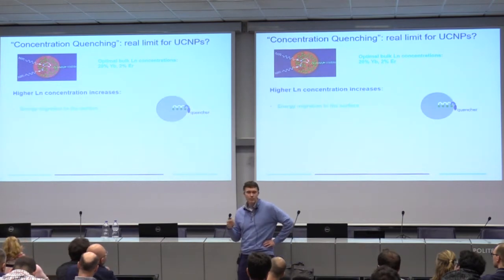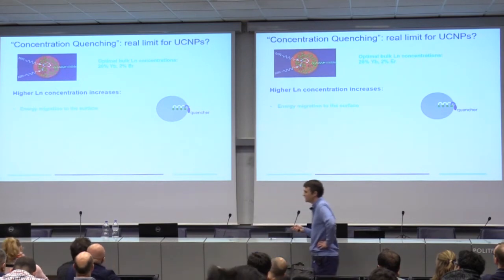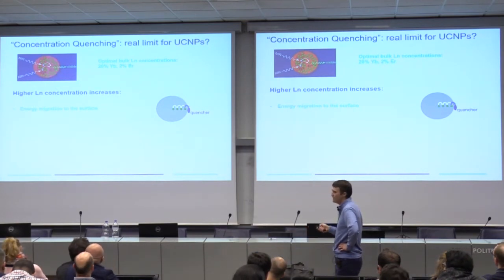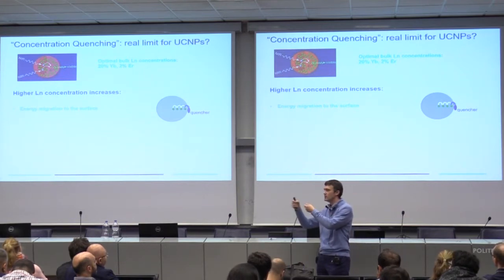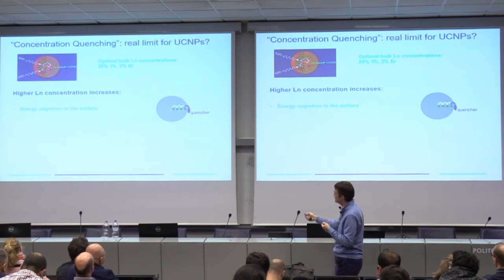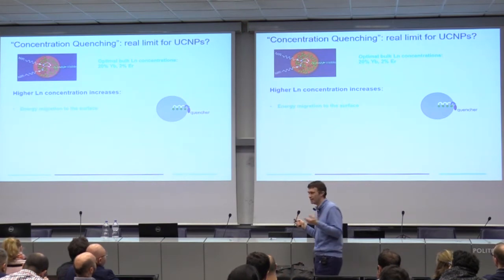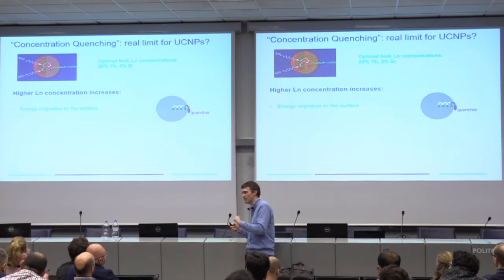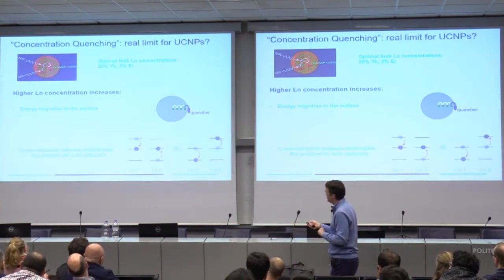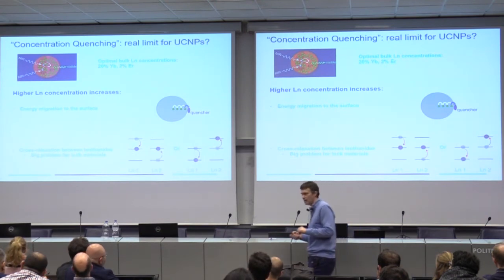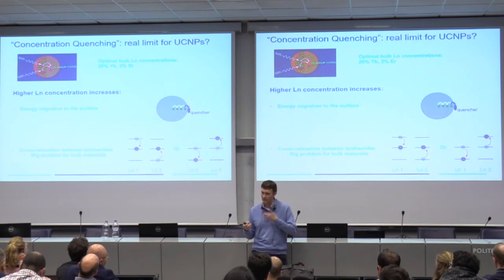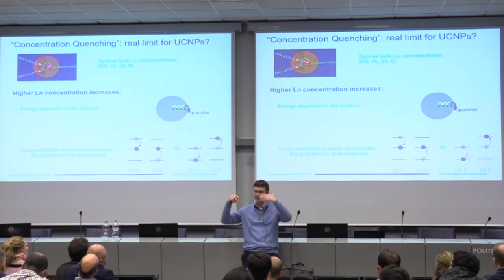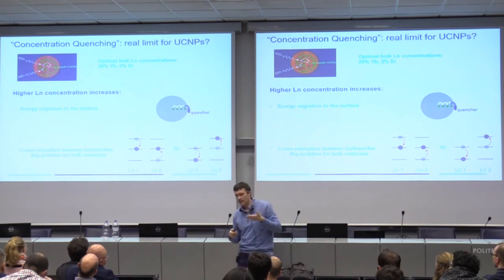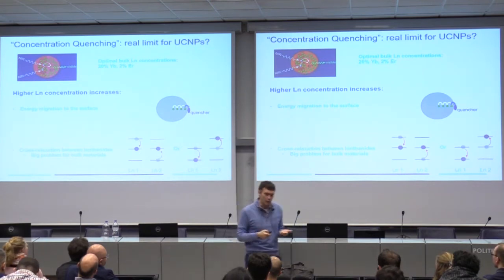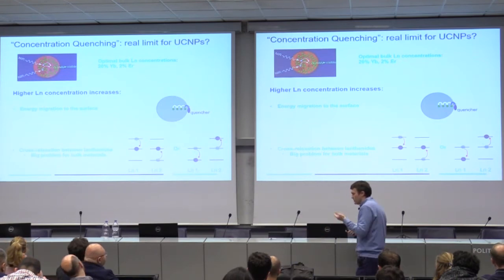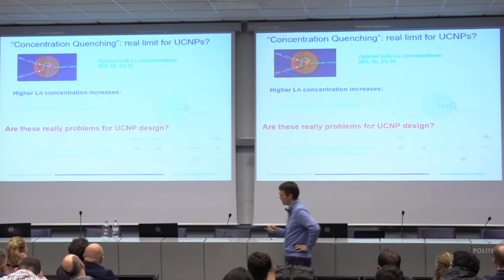So what happens if you put more erbium in there? Two main things come into play. The first is that as you increase the erbium concentration, it gets easier for energy to migrate from one ion to the next, and eventually energy can migrate all the way to the surface, and surfaces are bad, right? So that's one component of concentration quenching. The other thing that goes on is that you get cross-relaxation between the ions. Again you get energy transfer from one ion to the next, but they both end up in lower energy states rather than upconverting to higher energy states. And so this effectively reduces your upconverting quantum yield in these materials. This is known to exist in bulk materials. The question is, are these really problems for upconverting nanoparticles?